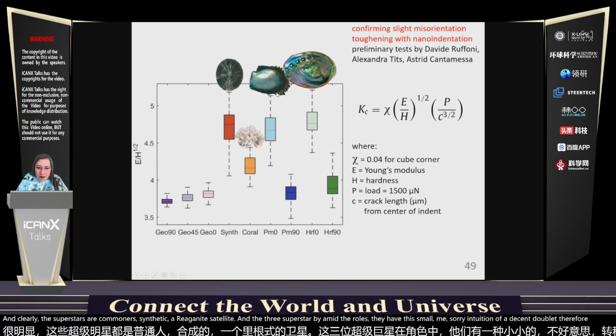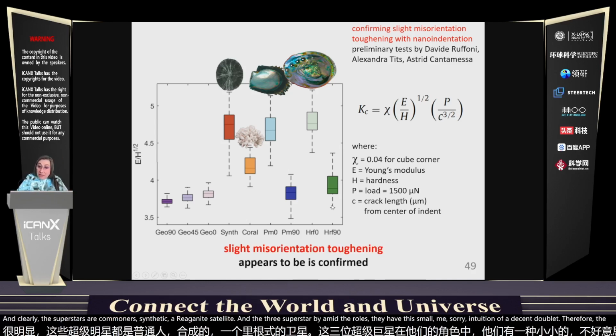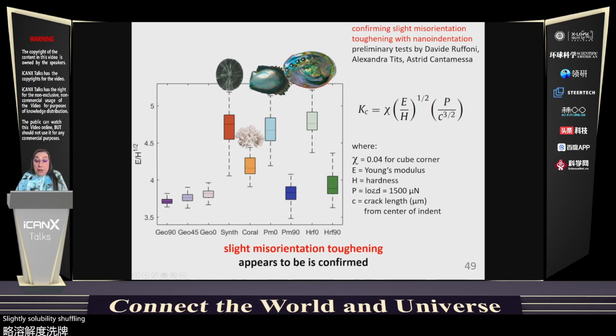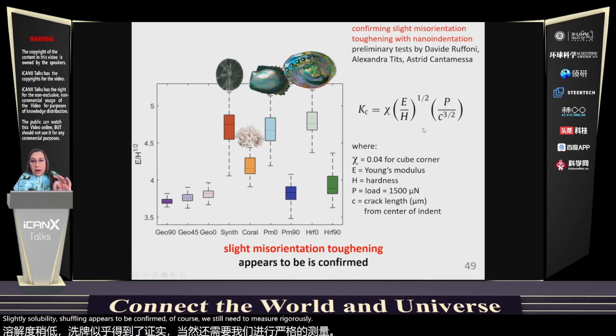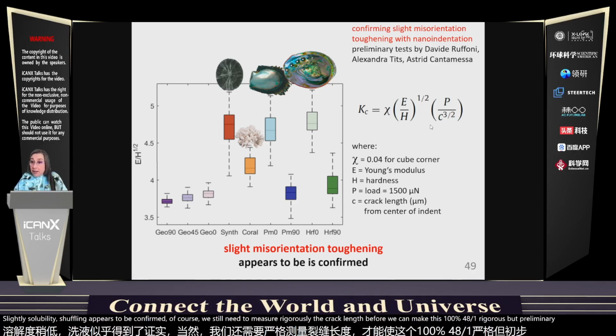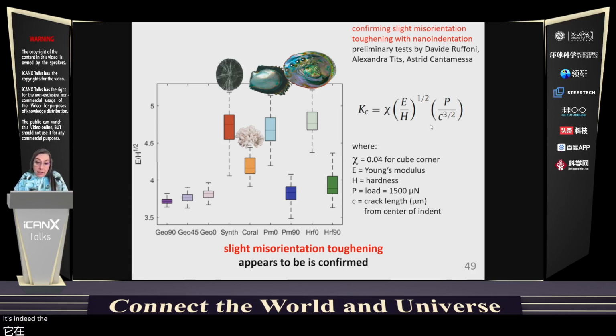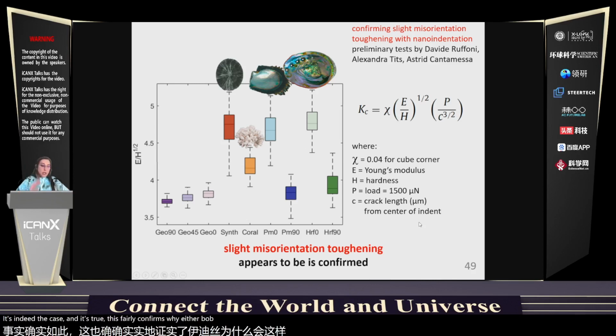Therefore, the slight misorientation toughening appears to be confirmed. Of course, we still need to measure rigorously the crack length before we can make this 100% quantitative and rigorous, but preliminary data appear to indicate that it's indeed the case. And if true, this really confirms why it evolved convergently.